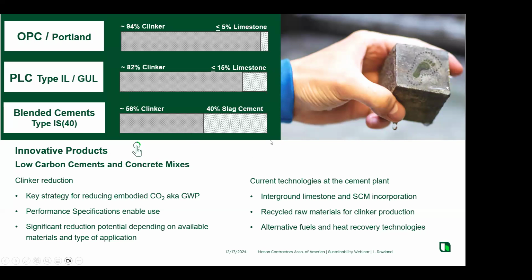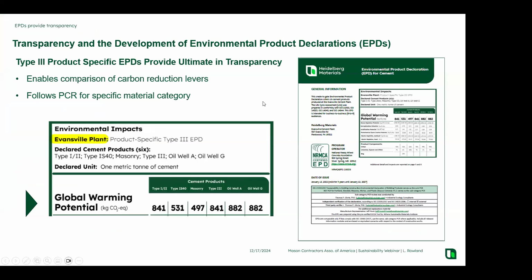So we've put in 40% slag, with the clinker at 56%, and then we've got a little bit of limestone and gypsum in there to round out those numbers. So blended cements are very much going to be in the future, not only for Heidelberg Materials, but the entire industry will be going towards those. I already said that a standard Portland cement has a GWP, a global warming potential, of 919. And you can see here for the type 1-2 that they manufacture at this Evansville plant, it's 841. So that's already much lower than the industry average. It's a very efficient plant. And then you can see here for the type 1S40, that's only 531. So we're getting down near our targets.